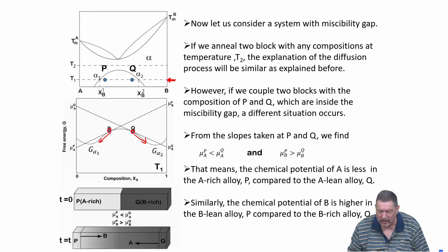But if we now again apply the description based on chemical potential gradient, then it comes out correctly. So that means that the diffusion serves to make the gradient of the chemical potential less steep. So the description based on chemical potential gradient always describes it in a correct way, so that the diffusive flux coming out of the equation is in the correct direction.